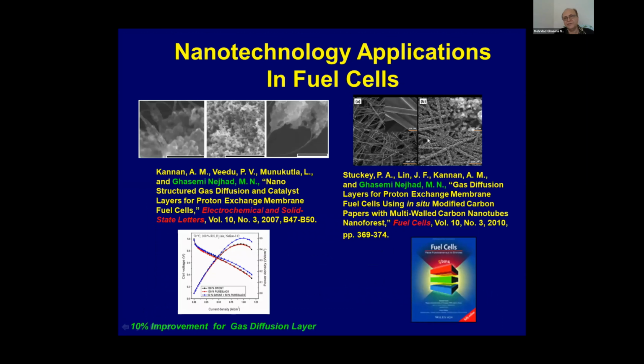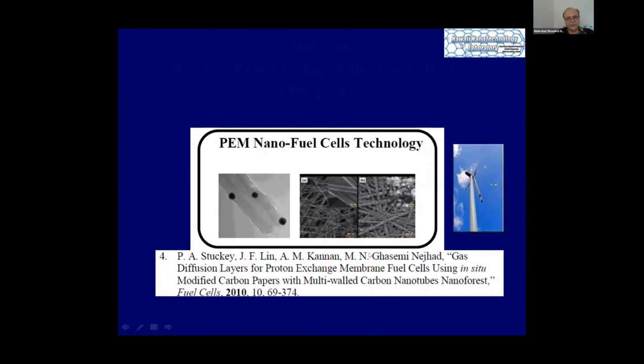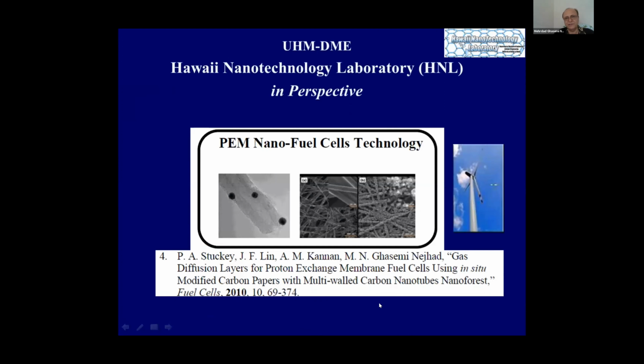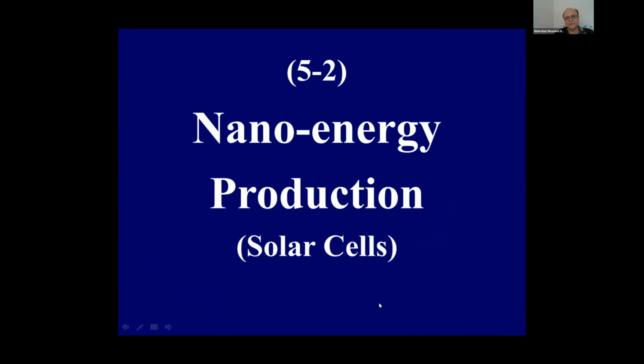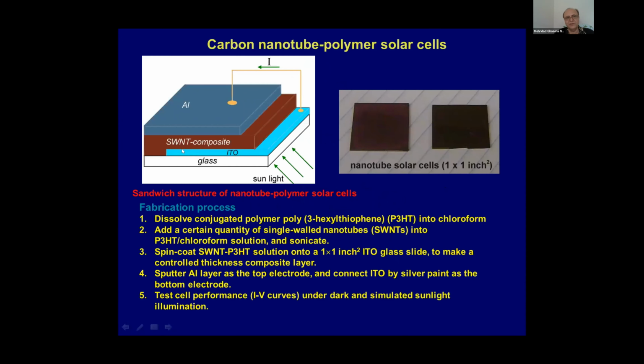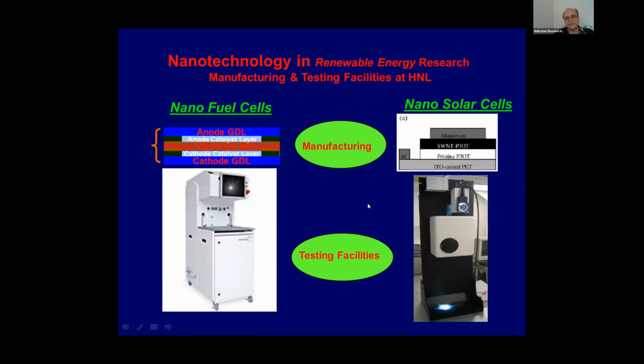Also, we use Nanoforest technology for the gas diffusion layer, and we got, again, a 10% improvement in fuel cell performance while saving on moisture production, because carbon nanotubes are hydrophobic and they repel the moisture. So that's the improvement of the fuel cell. Also, people use P3HT and P3OT for solar cells, polymer solar cells. So we use carbon nanotube and graphene to improve the performance of solar cells using nanotechnology.